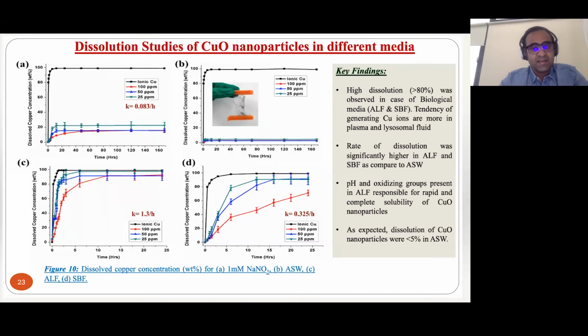And what we see is that these nanoparticles in biological fluid can actually have a dissolution all the way up to 100%. So if you look at figure A, B, C, and D, figure A is a deionized water analogue. Okay? In deionized water, these copper oxides do not really dissolve that much. So the dissolution is up to 20%. Artificial seawater is a medium which is analogous to environmental application. And in artificial seawater, these nanoparticles agglomerate because of a very high ionic strength, and they precipitate out. As a consequence, you do not get a very high dissolution. The dissolved concentration is less than 10%.